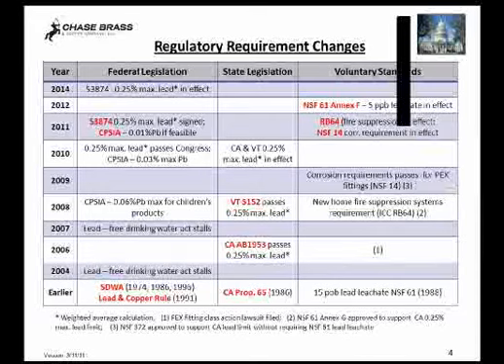In addition, in order to meet the 15 parts per billion of the Lead and Copper Rule, they started to use surface treatments to remove surface lead, so that in that standard laboratory test that's conducted by a number of certification agencies, they would be able to pass the 15 parts per billion and hopefully prepare them for the 5 parts per billion lead leachate that's required in NSF 61.